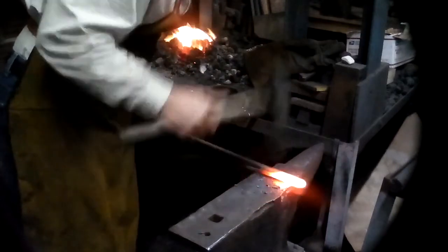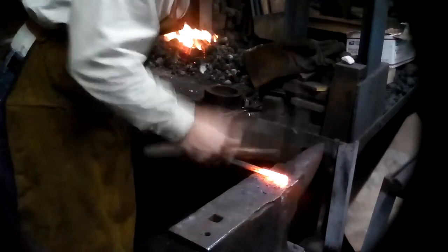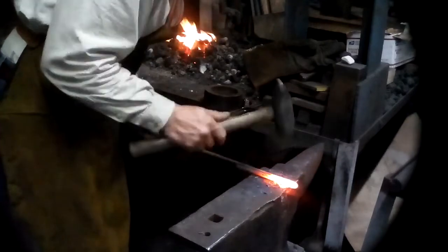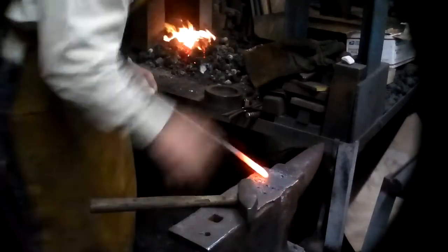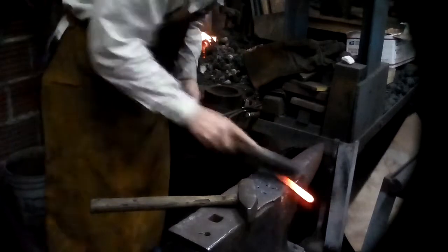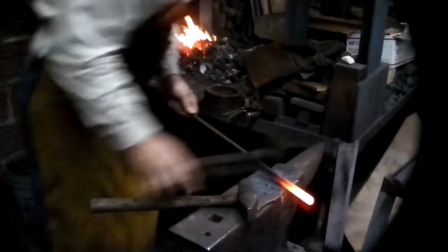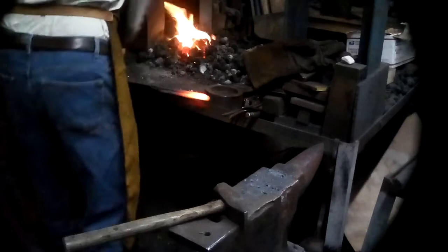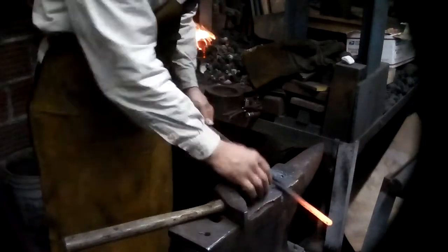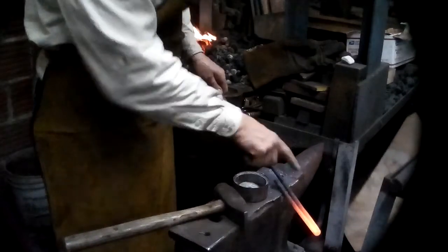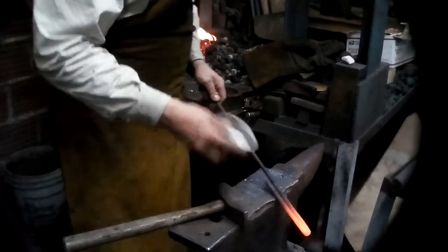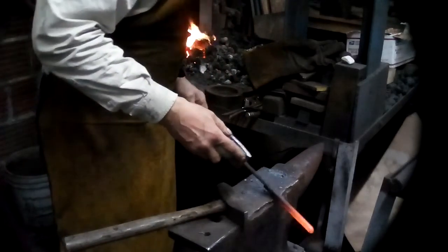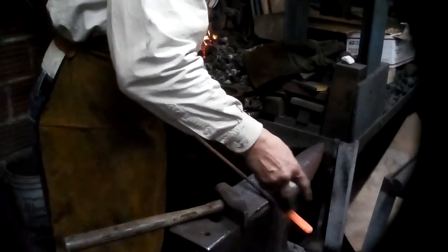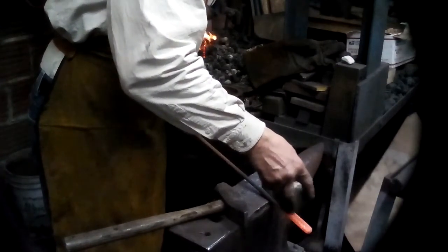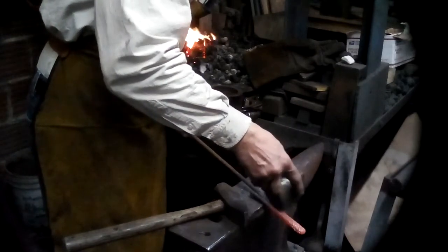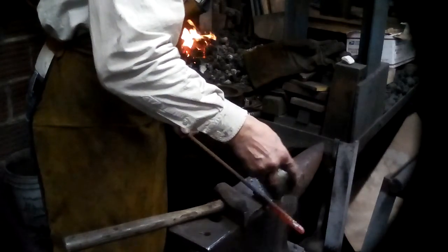Very gently. This is a round rod, and one reason that it's easier to do a forge weld on is that it's got a natural scarf to it. The shape of the rod will let the flux escape. A lot of people who have trouble with forge welding have two problems. They either don't have a pathway for the flux to escape. You need to have some way for that stuff to get out, and or they don't know that flux is not glue. You want just a tiny bit of flux on there. You don't want to put a huge amount.